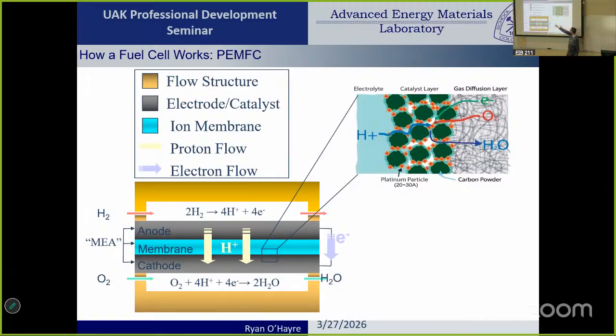Okay, so protons come in, oxygen from the air comes in, and they all have to meet. So they all have to meet on a platinum catalyst particle in order for this reaction to occur. Because you see, it needs oxygen gas, it needs the protons that are being supplied by the electrolyte, and it needs the electrons that are coming in. And when all three of those species meet on a catalyst particle, we call that a triple phase boundary. So you have the electrolyte phase that's supplying the protons, you have pores, gas phase, that's supplying the oxygen, and then you have electrons in the catalyst. So you need all three phases, so we call it a triple phase boundary. So every time you get one of these little triple phase boundaries, you can have the reaction.